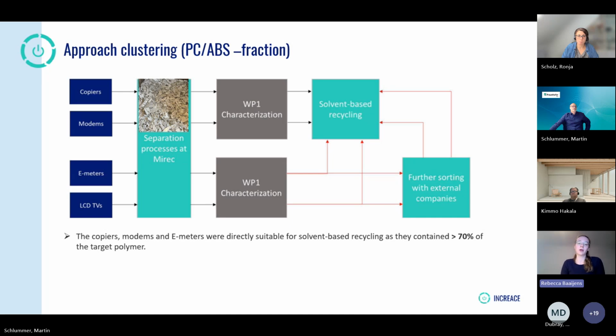So all four of them were again processed separately over all the lines to end at a fraction that contained PC ABS. For fractions such as the copiers, but also the e-meters that are predominantly white plastics, we could use near infrared separation to sort out only PC and ABS without losing a massive fraction in terms of black plastics. And these plastics were then either sent to solvent-based recycling or they also went to mechanical recycling and compounding. And here we saw that the majority of the copier, modems, and e-meter plastics that we got out of our process were directly suitable for solvent-based recycling, which is also the next part of this crash course.